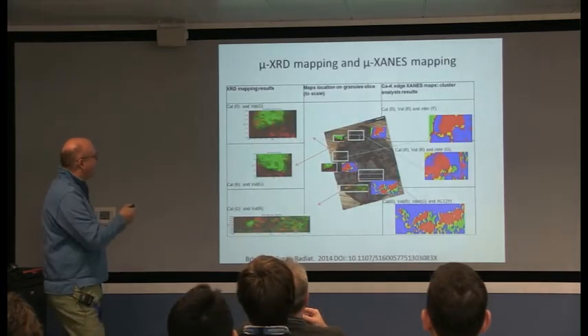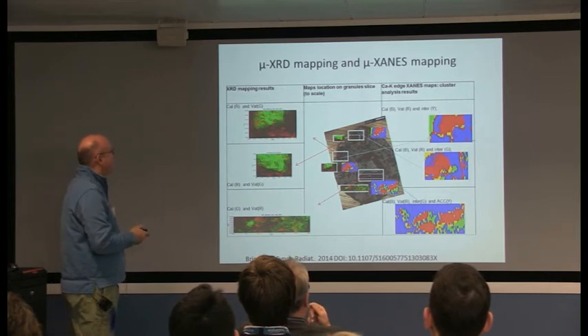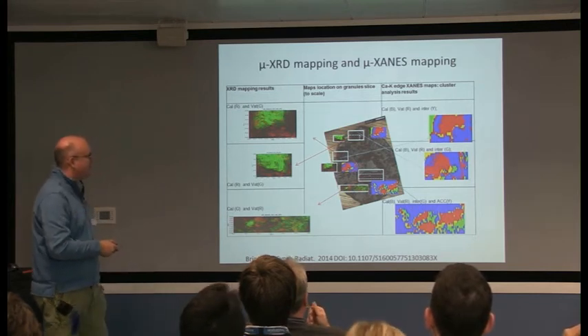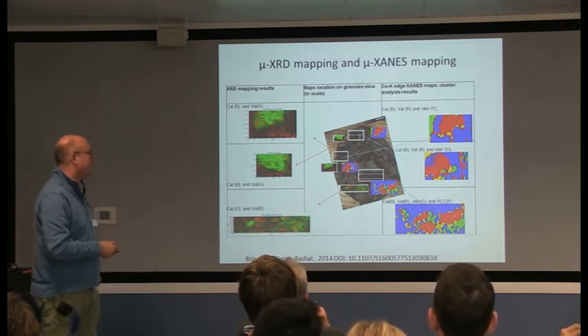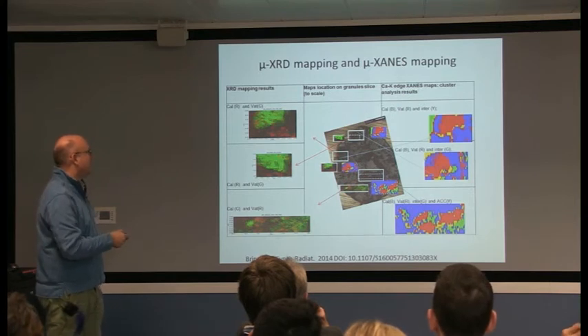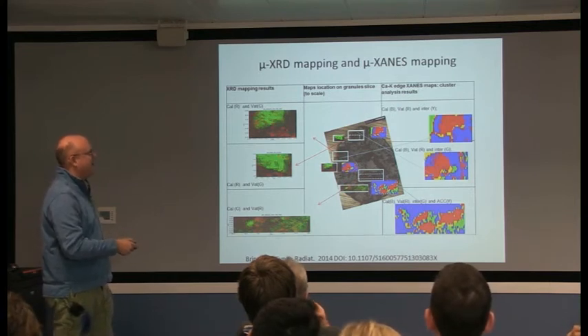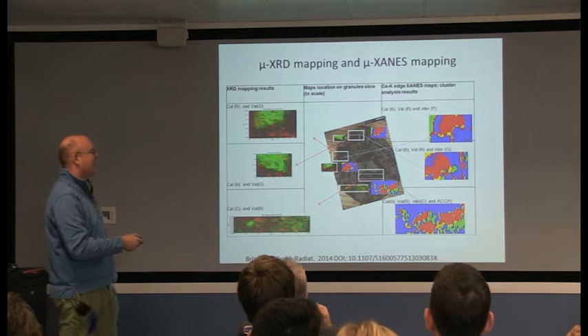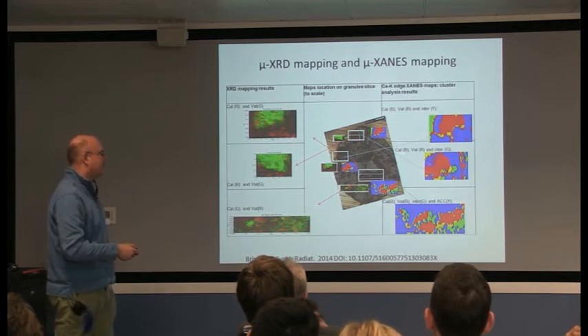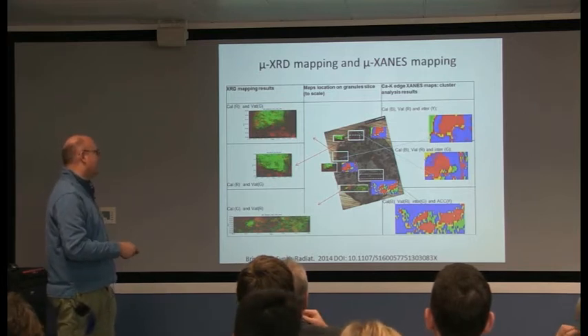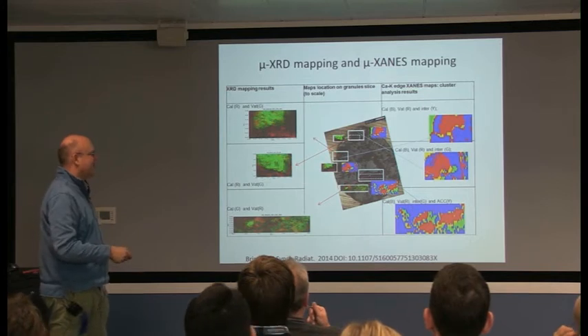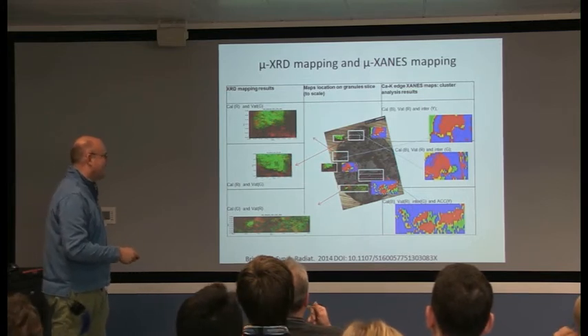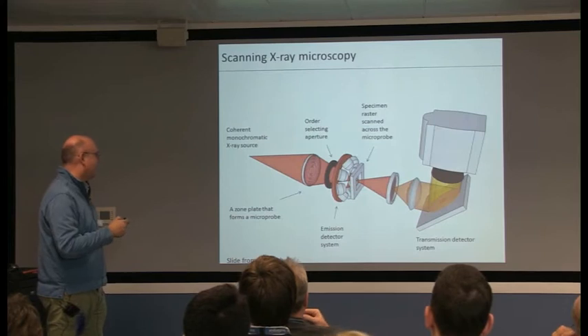We do micro XRD and micro XANES on I-18. This is a calcium carbonate granule, similar to one you saw on the slide earlier, and we can do the diffraction and the XANES mapping and compare it. So this is looking at calcite, vaterite, and mixed phases between them, comparing the XANES results and the diffraction results. Luckily, to a large extent, they agree, and we published that this year.